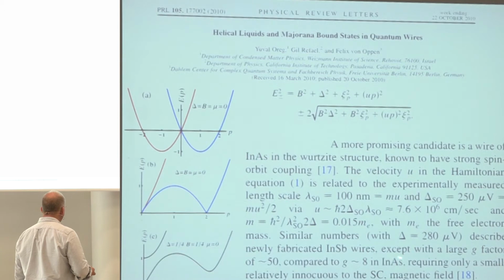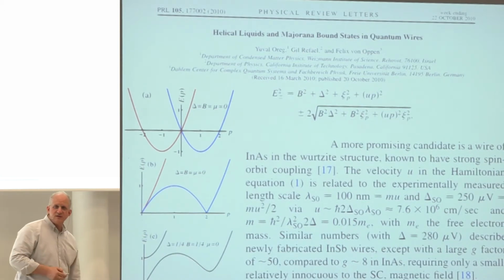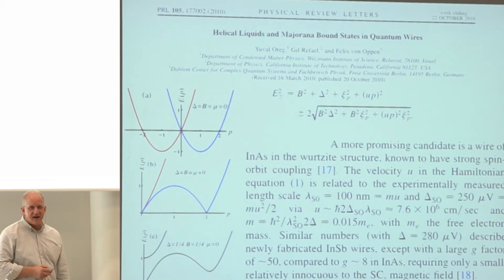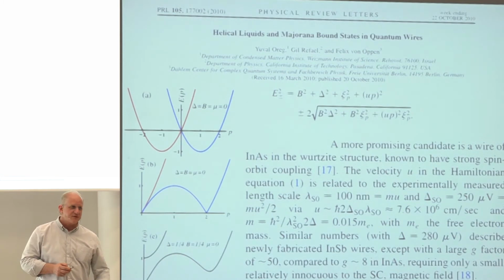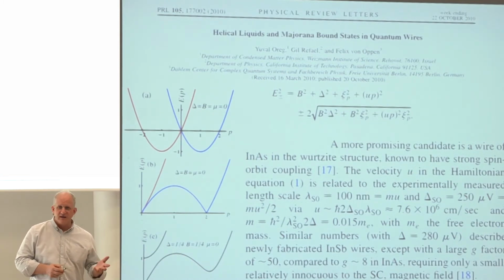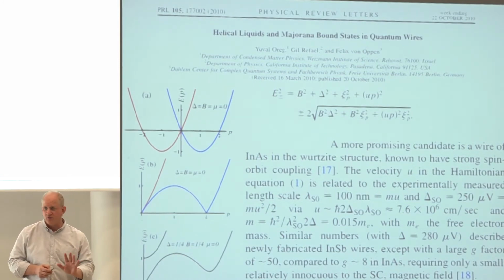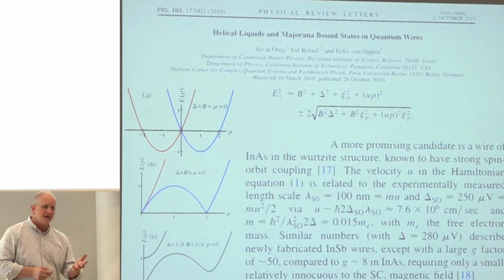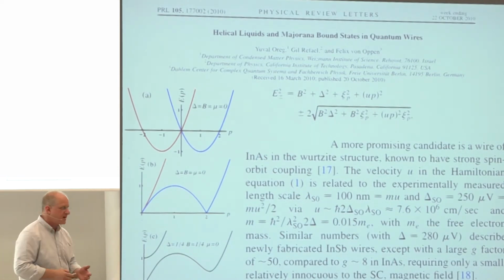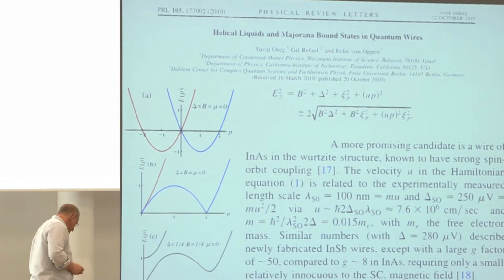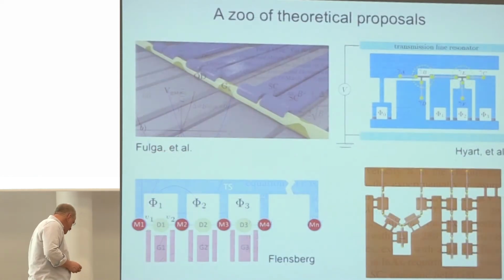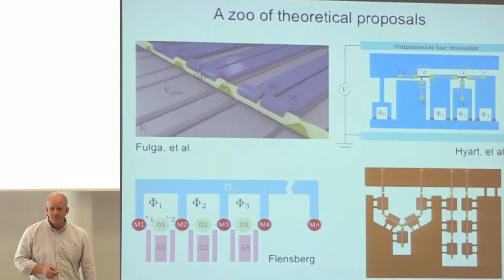So I'm going to be talking about experiments in indium arsenide. Some other experiments have been done in indium antimonide. But these are the materials that, because they're small band gap semiconductors, they have strong spin-orbit coupling and greatly enhanced G factor. And those are the two criteria that we need. And of course, they have to be able to be proximatized by coupling to a conventional metallic superconductor. But if we can do it, the numbers look good.